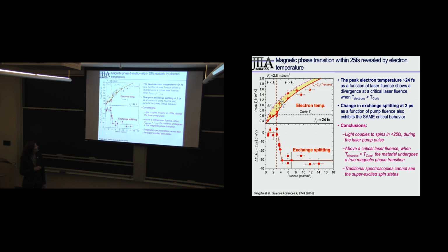we heat gently so that we stay below the Curie temperature, the exchange splitting collapses initially but then recovers very quickly. But if we heat the electrons above the Curie temperature, the exchange splitting collapses and stays collapsed, indicative of a magnetic phase transition. And it connects this ultrafast phase transition to the equilibrium behavior, because essentially this is the same result you would get if you heated up the magnet on a hot plate.